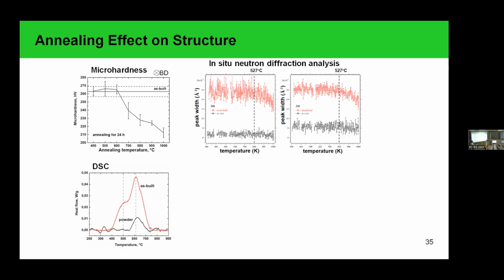At the next stage, we also decided to analyze the effect of heat treatment on the material behavior. For this, we annealed our materials for 24 hours at different temperatures, from 400 degrees Celsius to 1000 degrees Celsius, and observed a drop of the microhardness after annealing at 700 degrees Celsius.